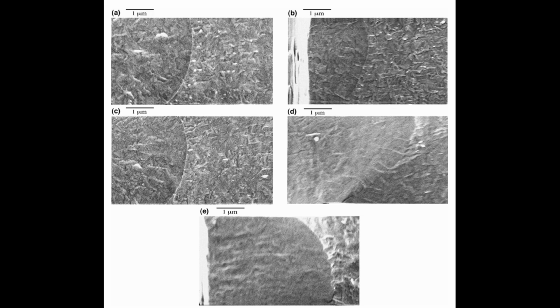Okay, let's try and wrap this up then. If you had to boil it down, what's the main takeaway from this deep dive into breaking tiny things? I think the core insight is how this team managed to measure something incredibly difficult, fracture toughness at the microscale, using this really innovative on-chip testing platform. Right, moving the test onto the chip itself. Yeah, creating those super sharp cracks, dealing with the processing stresses, and cleverly using displacement and FEA to get the numbers. Their initial result gave us that median value of 1.1 MPa·m^1/2, which is valuable.